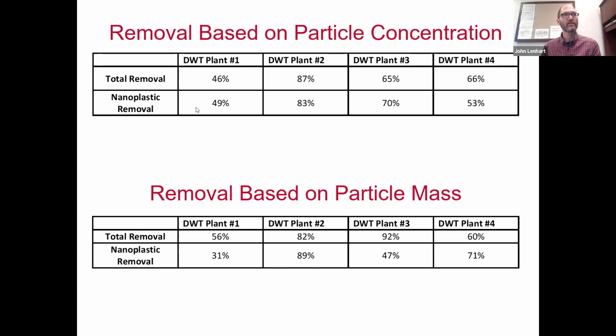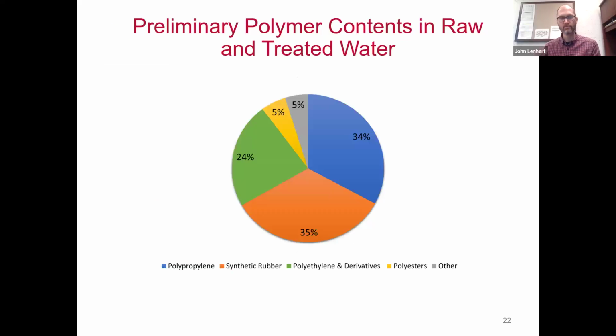In terms of the nanoplastics, for the most part, we see that it tracks pretty well with the overall removal. So the plants are removing roughly all plastic types equally well when you're looking at particle concentration. There's a slight difference when you're looking at particle mass, because on the basis of mass, the plants are removing the larger plastics to a greater extent than the smaller. So in some instances, we see on a mass basis that only 31% of the nanoplastics were removed.